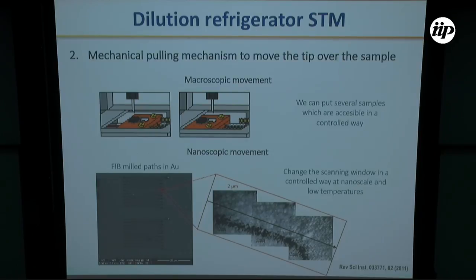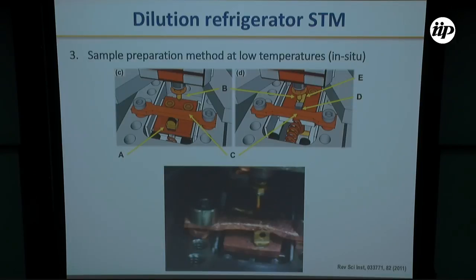Well, our STM has a mechanical pulling system that allows us to change the relative position between the tip and the sample over a macroscopic distance of a few millimeters with a precision of some tens of nanometers. And this is useful, for instance, to be able to prepare the tip in situ and at low temperatures. It also allows us to cleave the sample in situ at very low temperatures.